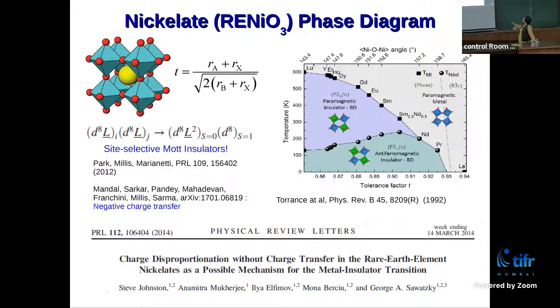For these transitions, people so far have thought about what is known as a charge disproportionation transition. Rare earth is 3+. I will have quite a bit of chemistry, so I hope that will be fine. So rare earth is 3+. If you just do a charge balancing, nickel will be 3+. Nickel 3+ is d7. And nickel doesn't like to be d7, it likes to be d8. So the whole idea was you take two of the d7 ions, and that charge disproportionates into one d8, another d6. But that's really not the case.